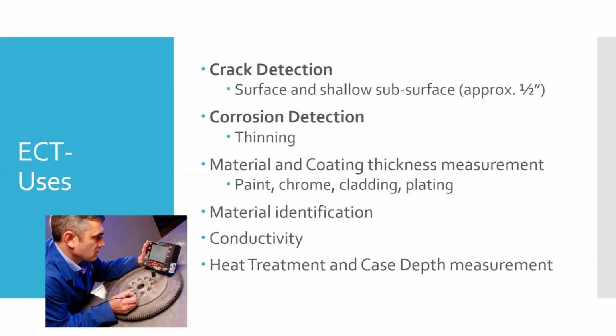And then because it can measure differences in material as you go deeper, heat treatment and heat treatment depth monitoring, again, to make sure the part's been heat treated properly, where you have a thick enough wear layer, but you haven't heat treated it so much that you lose that strength from the non-heat treated core of the material.